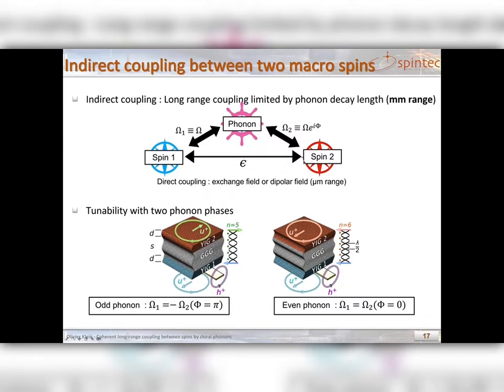Also, particular to our system, there are two types of phonon. We have odd phonons, which means that the phase at the bottom is opposite to the phase at the top layer, as you can see here. For even phonons, the phase at the top and bottom layer are the same. Mathematically, for odd phonons, the coupling strength of the bottom layer is opposite to the coupling strength of the top layer, while for even phonons, they have the same sign, the same polarity.